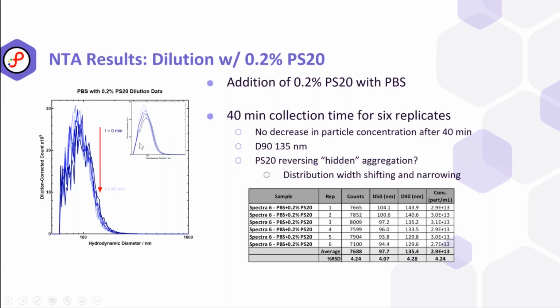And so if we look at the inset here, we can see that this single population mode is shifting to smaller size, and there's a concomitant increase in concentration of those particles. So really what's happening is the band is shifting and it's narrowing at the same time. So we don't see a drop in concentration, but we're seeing a change in the particle size.